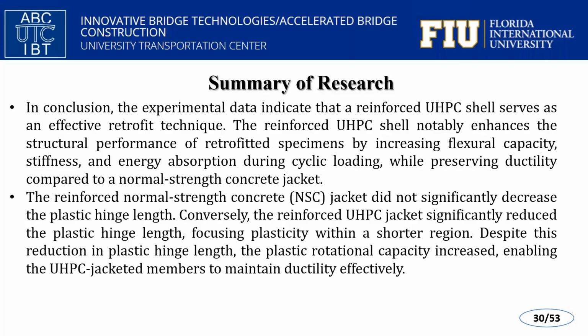The reinforced normal strength concrete jacket didn't significantly decrease the plastic hinge length. Conversely, the reinforced UHPC jacket significantly reduced the plastic hinge length, focusing plasticity within a shorter region. Despite this reduction in plastic hinge length, the plastic rotation capacity increased, enabling the UHPC jacketed members to maintain ductility effectively.